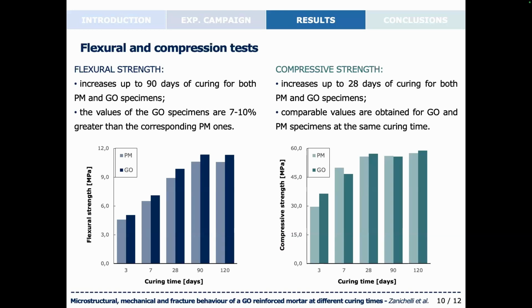Whereas on the right side of the slide, we have the compressive strength results. In particular, the compressive strength increases up to 28 days of curing for both specimen types, and then it remains quite stable up to 120 days of curing. And in this case, comparable results have been obtained for the two types of specimen, especially in the stable part, that is from 28 to 120 days of curing.